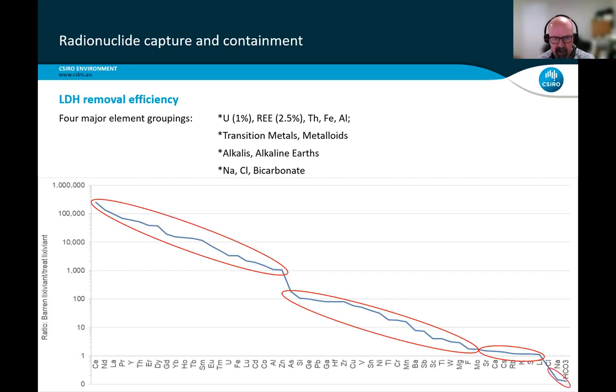And the last grouping there is what we had a net addition to. So they fell below that 1 ratio line. So we had some chloride because we added some magnesium chloride. We had sodium because we added sodium hydroxide, and we added a bit of bicarbonate. Again, who cares? We added some NaCl and we added a bit of bicarbonate to the system.